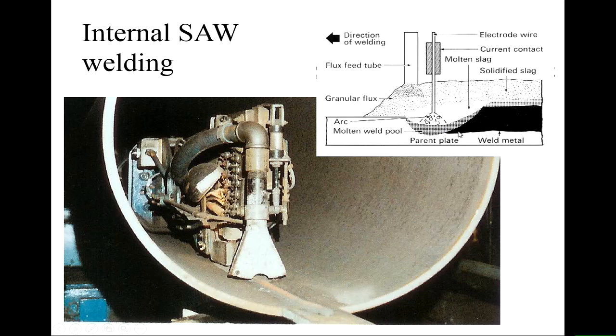Now if you did that in air, in any welding process in air, the atmosphere will affect both the stability of the arc and also the surfaces that you create. The surfaces get hot because you've melted the material. It's at 1500 degrees C if it's steel. It will react with the air to form an oxide. And too much oxide in the weld pool means a very brittle weld, and you don't want that to happen.